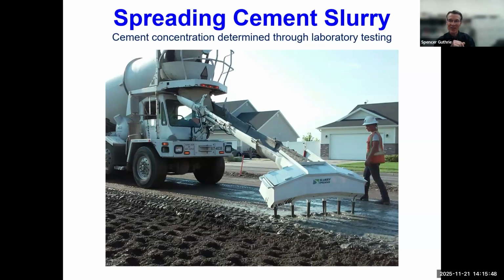And I also want to point out one more thing. This is related to concrete technology, where we have an advantage using slurry compared to Portland cement powder beyond what I've already described. Do you know that we can add hydration stabilizer, sometimes referred to as set retarder, to a concrete or to a slurry to slow it down? So even though it's in contact with water and the cement is hydrating, we put in a chemical at the batch plant that cannot be added to dry powder, and we can give our construction crews another 2 to 4 hours of time to mix the cement slurry, to work it, shape it, and compact it.